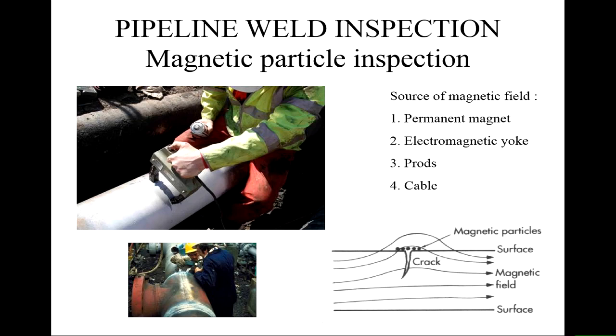The prods, the legs, and the cable to the power supply are really the only things you need. It's a very simple piece of kit. A bit of white paint is quite cheap, and being able to spray from an aerosol can some ferromagnetic powder means that you can do this on site, and you can test welds in complex shapes. So here is a T-piece being welded on with a shell structure, and the welds are being inspected to look for cracks.